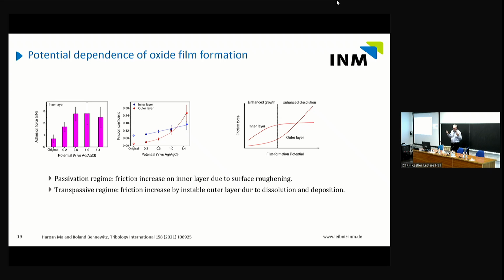So this brought us to this picture, which I sort of sketched initially, that the inner layer is essentially a hard and solid oxidation product, while we have metal oxide diffusing to the surface and actually into the solution, and in particular in the transpassive regime, when we actually dissolve the surface essentially by oxidation, then we have a lot of this squishy, squishy outer scum layer that is just loosely on there, but gives a lot of friction